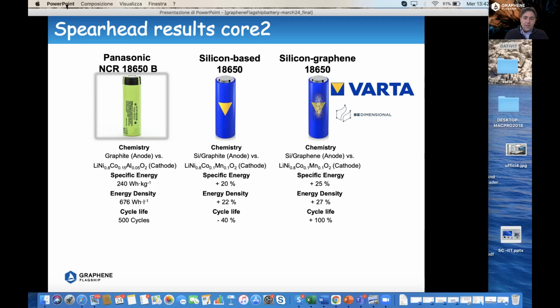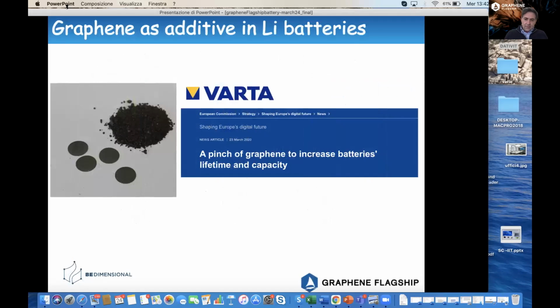For example, we were able to achieve at the industrial prototype level a specific energy density of more than 27% with respect to the silicon graphite, which is in turn better than the graphite anode, with finally and fortunately a very nice stability that is approaching the stability with the graphite anode. And there was a press release by Varta on this point last year.